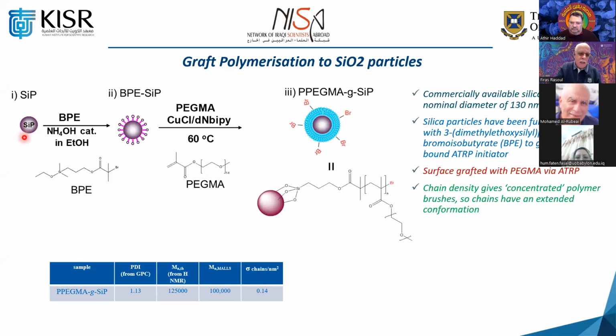We take the silica nanoparticle, we reacted it with that. If you see, I don't know whether it is visible for you, it is coupled like that in here. And of course, after coupling it, we did some free radical controlled polymerization. Before that, we introduced an initiator. This is the initiator. By the way, this coupling is happening with an ATRP initiator attached to it. Then we start polymerization using PEGMA, polyethylene glycol methacrylate, in order to start a polymer chain from that.